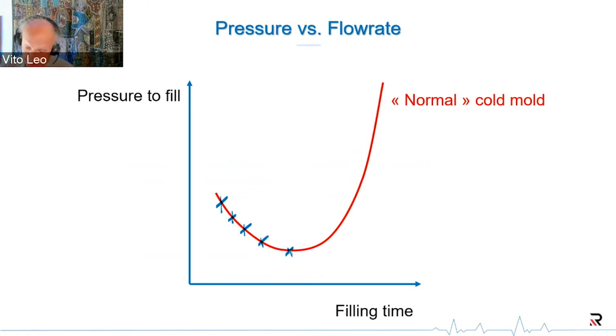But all of a sudden, in classical, normal cold mold injection molding, you will experience this dramatic upturn at some point. So the slower you go, the more pressure you need. Now where is that coming from? From the frozen skin. Because we are going slower, we give more time to the melt to freeze off. The actual thickness of the frozen layer will be higher, so the percentage of blocked channel will be correspondingly higher, and the pressure will go up.